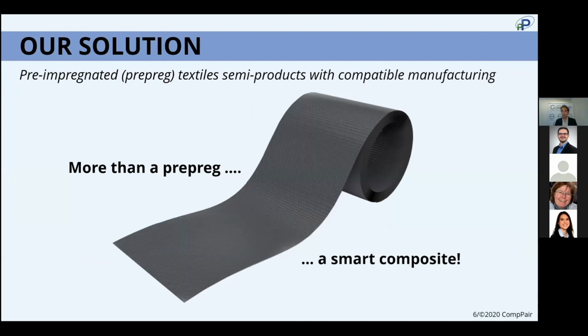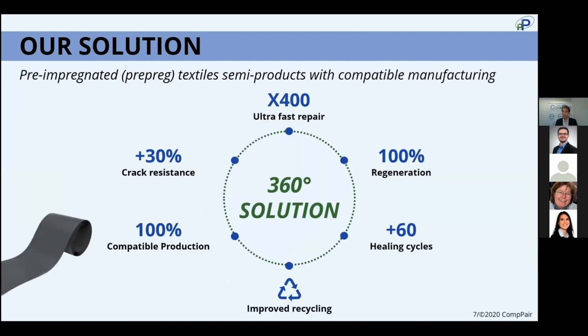What we are bringing as a solution is textiles, carbon glass textiles that are pre-impregnated with our resin chemistry, and it's more than a prepregs. It leads you to a smart composites. So what you will do with those prepregs is first manufacturing them, producing full composite parts with our prepreg products, and what we aim for is to have a full compatibility for you on your manufacturing line. Then what we are bringing when you will produce those composites is a better crack resistance, and you will have the ability to fully regenerate the damage multiple times, and most importantly, extremely fast. At the end of life, and this is why we are providing a 360-degree solution, is an improved recycling.